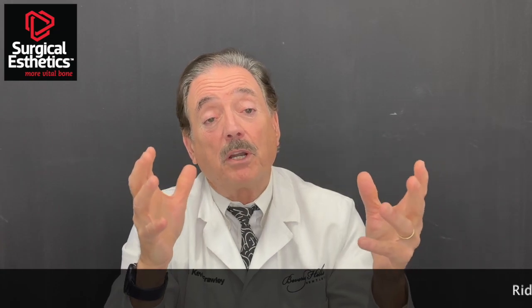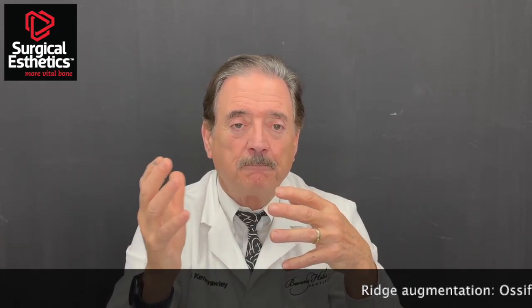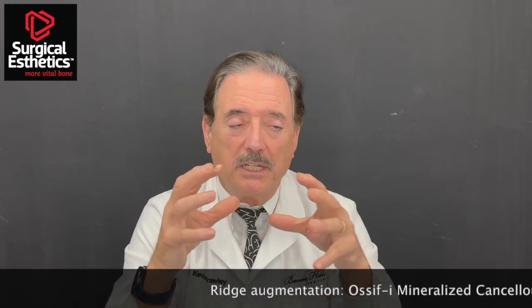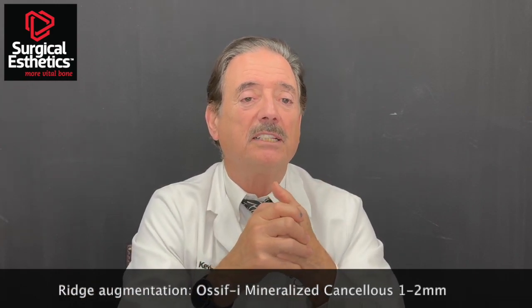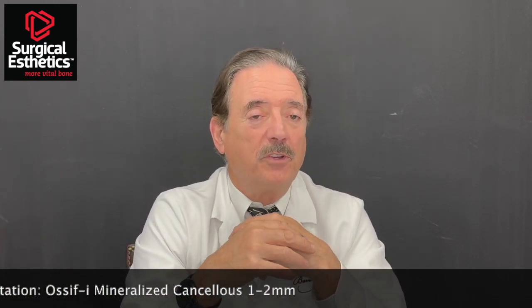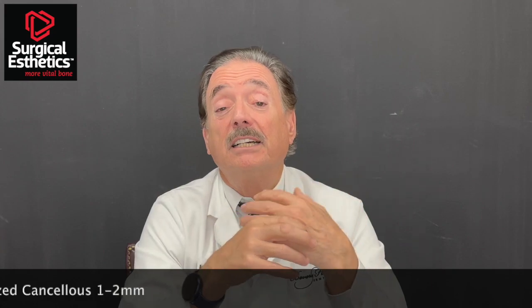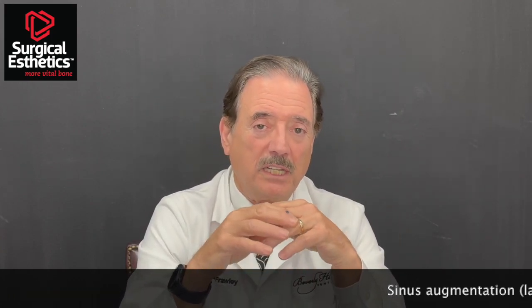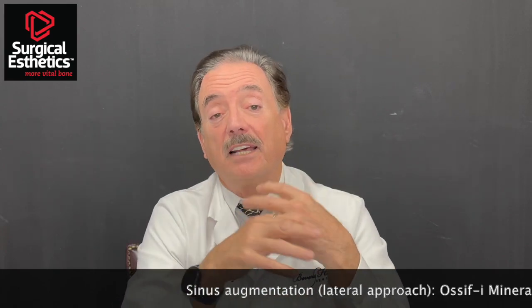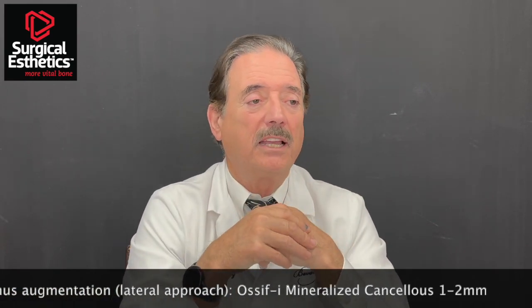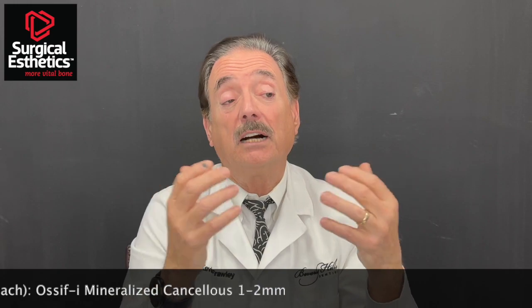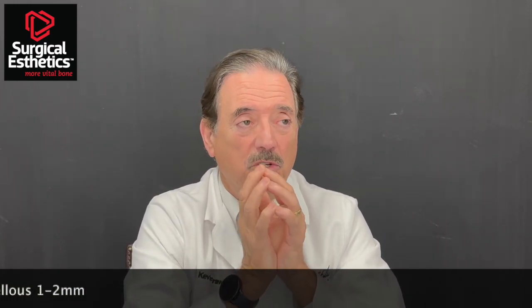The other option on particle size is a 1 to 2 millimeter. The 1 to 2 millimeter is definitely a larger particle size, and that would be good if you're doing a large lateral graft, where you're building up a large area, or sometimes if you're doing an open sinus, not an internal sinus, and you're really going to pack that well, then there's a good use for the larger material, the 1 to 2 millimeters.